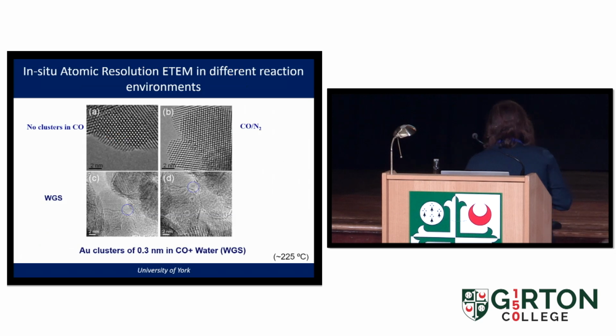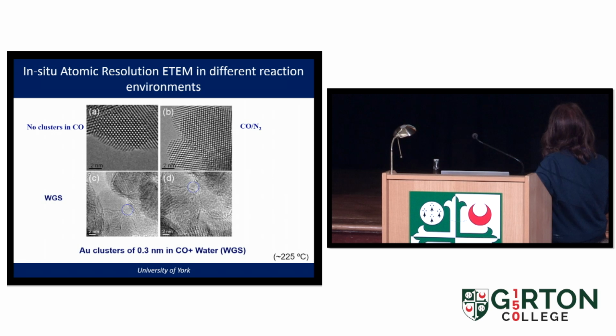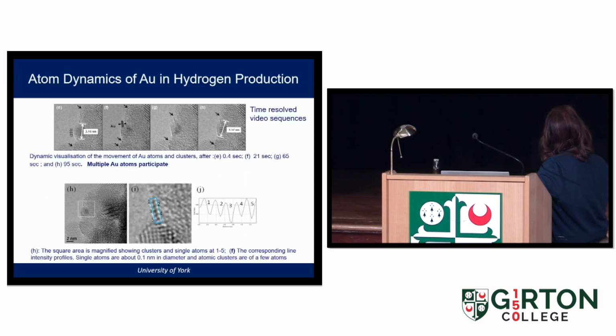We then put water and carbon monoxide together, and you can see as soon as you put water, gold comes to the surface. It's very reactive with water. And you can see that gold clusters and atoms come to the surface. You can also see gold atom dynamics. Lots of these single atoms and clusters are present under these conditions. This is initial. After 20 seconds, 1 minute, 1.5 minutes, you can see more and more atoms seem to participate in the reaction. We can confirm that with analysis here.